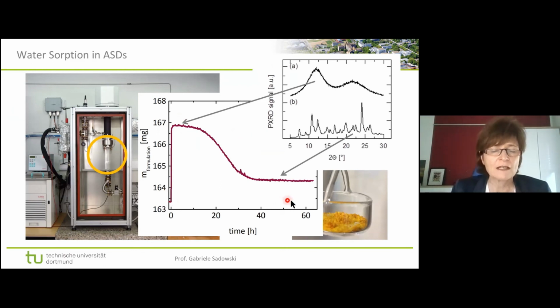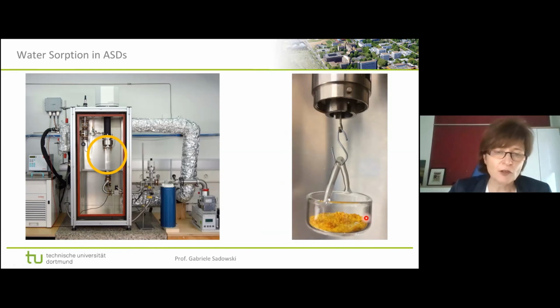But what we also do is the same thing with the apparatus. This can be a formulation, but of course we can do the same experiment with just the pure API. It can be crystalline or amorphous API. Experimentally, this is not a difference. I mean, this is a balance, and the balance just weighs the sample, whatever it is. I'm not sure for nifedipine, but we do this for several APIs. We have those sorption measurements, and this is, for example, what we also use to get the binary parameters of the system API water.